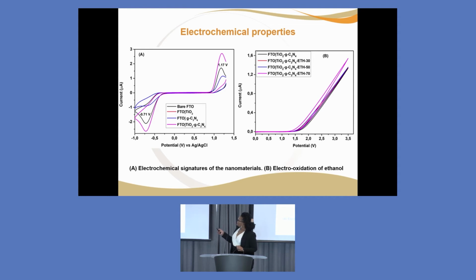Now we have applied our composite material in terms of the oxidation of ethanol. And we were using different scan rates when we were doing some oxidation. And if you're looking at the figure here and here, you can see that when we were doing some readings, we were focusing on the potential window of -1 to 1. But then now, if we are talking about the oxidation, we increased our potential window, because this is the range whereby the oxidation of ethanol or primary alcohol appears. And if you're looking at these different scan rates, you can see some changes in terms of the electron transfer.